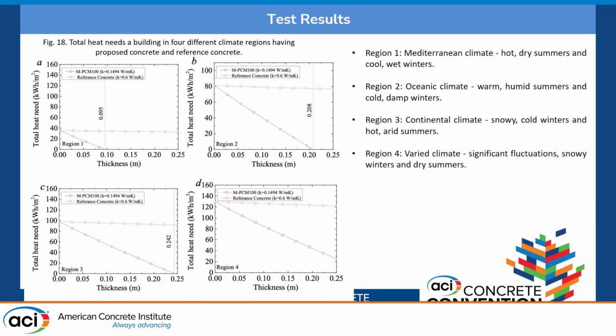We can actually go further and do some energy analysis. We can calculate the total heat needs for a building in different climates. We can do some climate adaptive tests here. We can change the thicknesses of our wall members, and we have compared this with a reference concrete, which has around 0.6 watt per meter Kelvin thermal conductivity, and we have our PCM specimen. For example, for region 2, a 20 centimeter specimen thickness wall can make the total heat need 0 for a structure in region 2, which is an oceanic climate. So this highlights the importance of the different climatic regions and the different thicknesses. We need to understand the climate adaptive techniques and technologies.